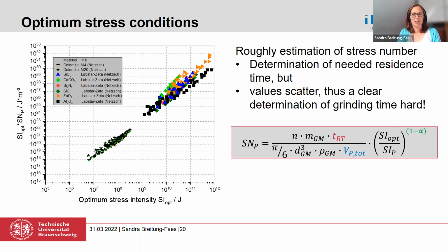So the deviation is about 2 to 3 decades, and I would say, okay, it's somehow describing what is happening there, but from this point of view, we should be a little bit careful to say it's the best thing to do to recalculate the grinding time. Nevertheless, you can do it for sure, and you can see that especially the scattering for the bigger mills is much lower. And my advice here would be, I can show you how to do it, but you should know the mill you would like to look at.